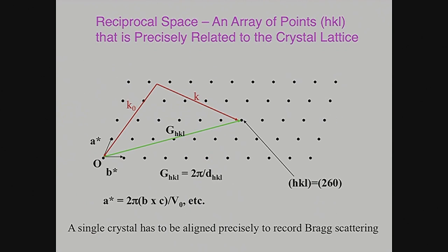And in order to get this Bragg scattering, you have to have a scattering triangle. This is your scattering triangle, with a scattering wave vector which brings you exactly to one of these reciprocal lattice points. So you only get scattering for particular values of the wave vector transfer, both in magnitude and in direction, when you scatter from a single crystal.